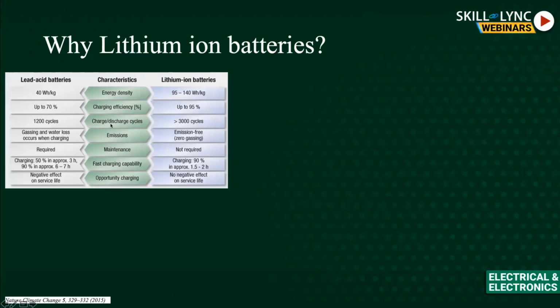Then charge discharge cycles. These are the number of times you can charge and discharge the cell without it completely dying and becoming unusable. Lead acid batteries only give you 1200 cycles of charge and discharge, whereas lithium ion batteries go beyond 3000. Current technologies, if tailored specifically, can go even up to 5 or 6000 cycles. And in terms of emissions, there is a lot of gassing and water loss when charging lead acid batteries. Lithium ion batteries are emission free, and that's why we call them clean technology.